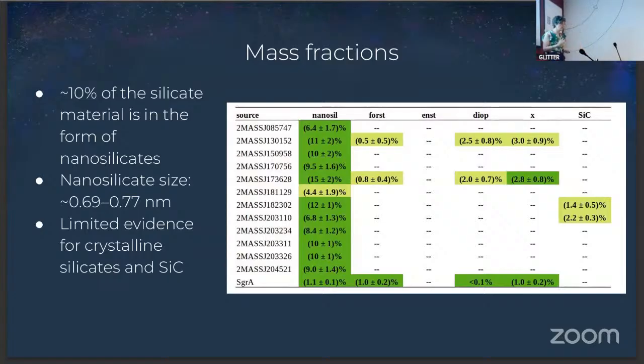Okay, so what amounts are we talking about? So the previous table showed evidence that it was there. This table shows the amount of nanosilicates that we find. And we find of the order of 10%, basically, in the sightlines that we're interested in. Note that I also included Sagittarius A star here, because I fitted it also, and we find a much lower fraction of nanosilicates. Sagittarius A star does show some forsterite to be there of the order of 1%, which is within the limit that we said 20 years ago, which was less than 2%. The other sightlines do not really show evidence for forsterite except here and here, which maybe contain a small amount.